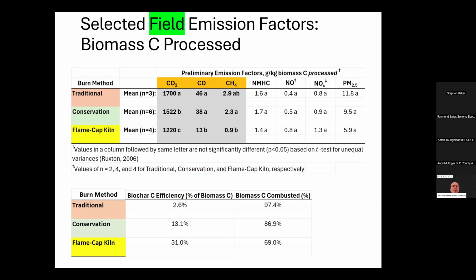We can take it one more step and look at it from the standpoint of the biomass carbon processed. So here we're talking about carbon efficiency. And when we do that, we see that, again, CO2 and carbon monoxide show some differences, particularly for the flame cap kiln. But methane in particular also shows a difference, at least between the conservation burn and the flame cap kiln, where there's a significant difference, with flame cap kiln methane levels being quite a bit lower than the other two, or than the conservation burn anyway.